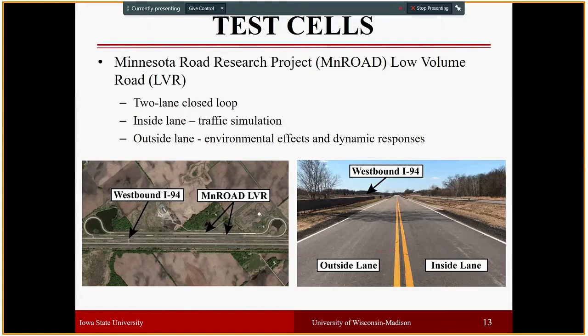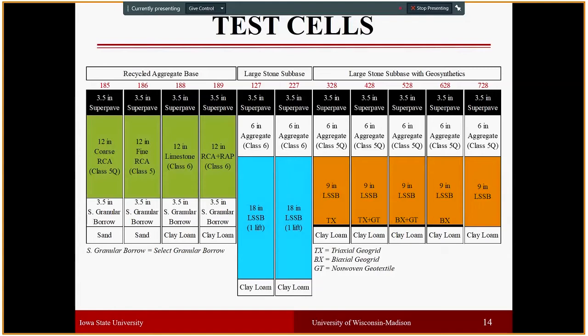So we have 11 test sections on the low volume road side of the MnROAD. And this is a schematic picture of the test sections from our construction report. We have recycled aggregate bases and large stone subbase built with higher thickness, and 5 large stone subbase sections with different types of geosynthetics or combinations of geosynthetics. On top of the large stone subbases we have class 6 conventional aggregate and class 5Q conventional aggregate, and all test sections are built with 3.5-inch HMA hot mix asphalt.